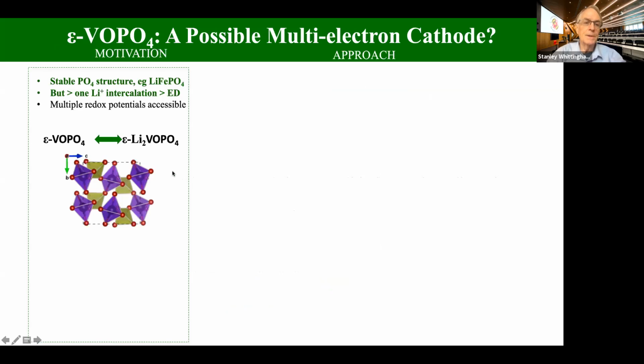So let's just look at this structure briefly. We're looking mostly at the epsilon variation of this material. This is a material first made by Alan Jacobson at Exxon. These materials are good oxidation catalysts in the chemical industry. And I'll show you in a moment, this is causing us some problems. But this is again a tunnel structure, so it's very, very stable, with phosphate tetrahedra and vanadium oxide, very strained octahedra. So we have this nice tunnel structure.